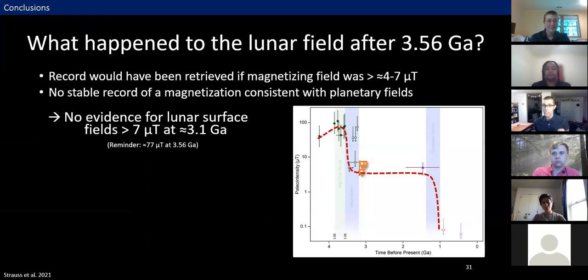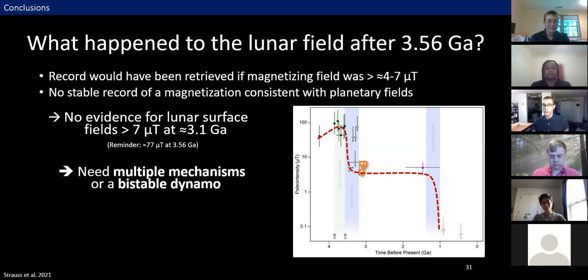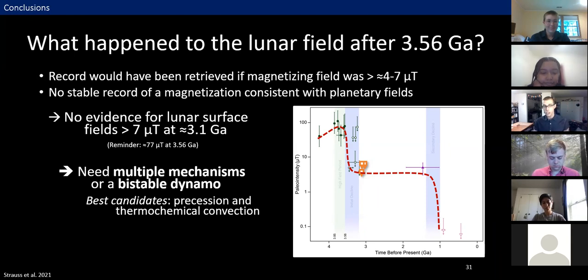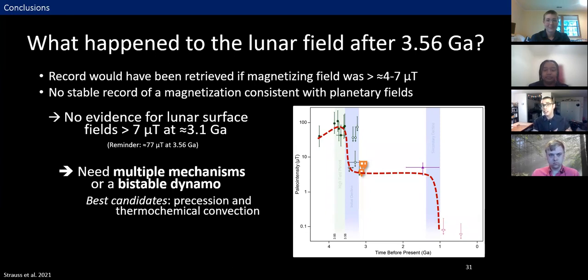Now, in order to explain this, we need either multiple mechanisms of field generation or a bistable dynamo that could have sustained field intensities in a high field and low field state before collapsing. We think that the most likely candidates here are a combination of a precession dynamo and thermochemical convection. The idea being that a precession generated dynamo could have accounted for the strong fields observed during the high field period until the increasing distance between the moon and the Earth was sufficient to remove the moon from the gravitational state necessary to produce the fields.